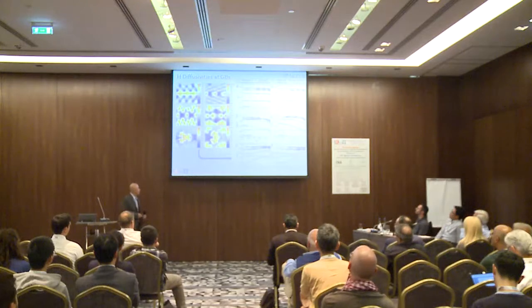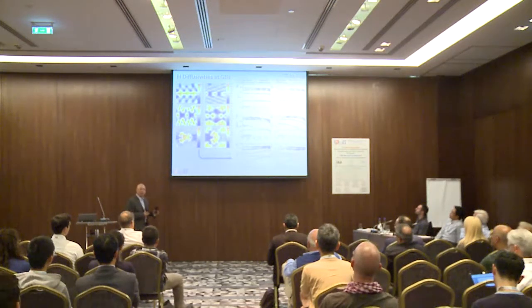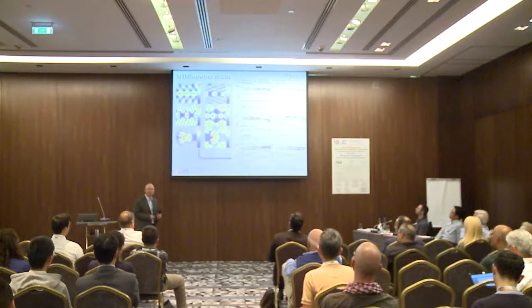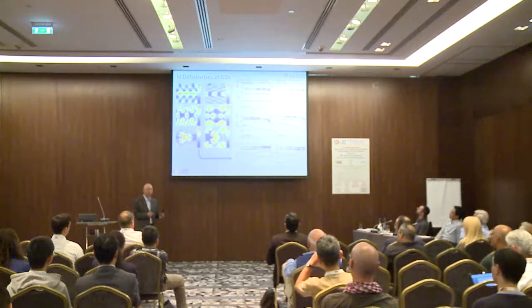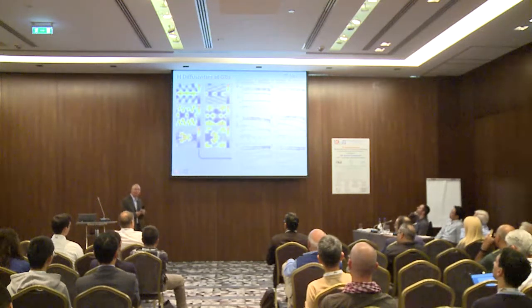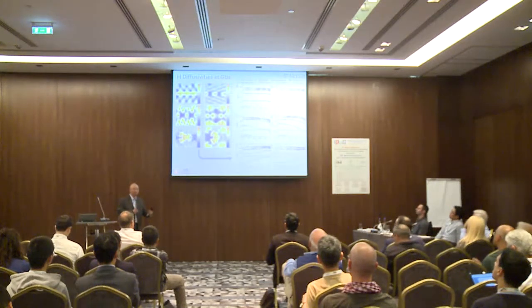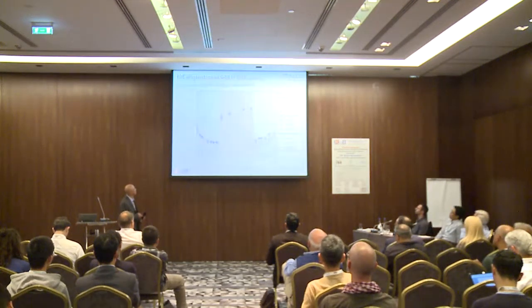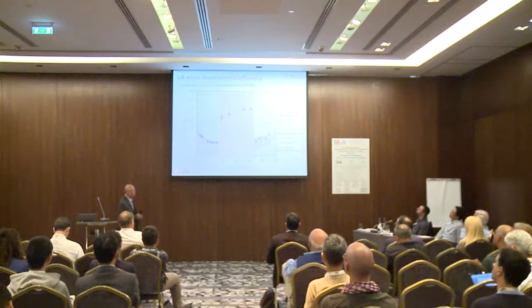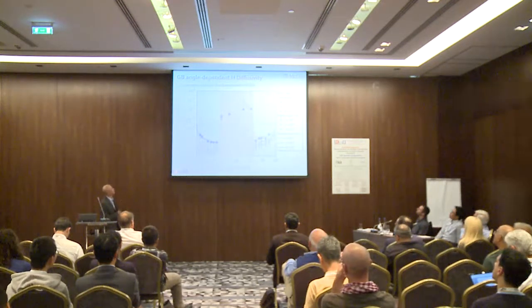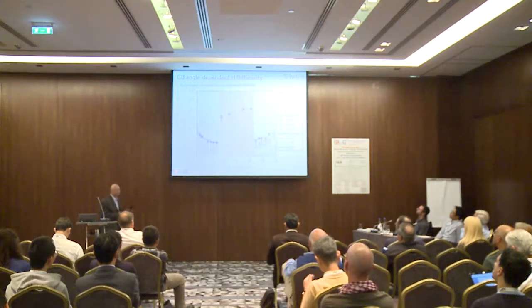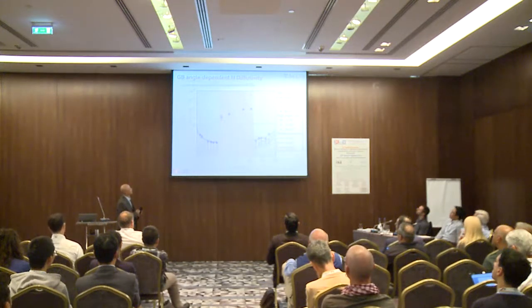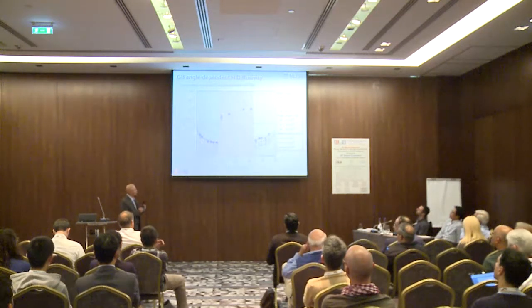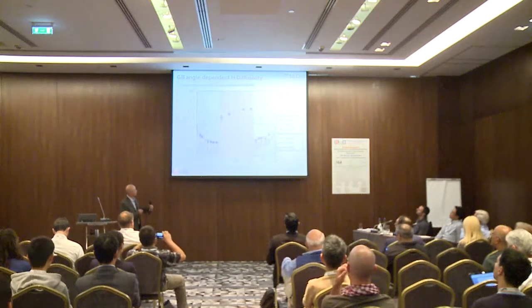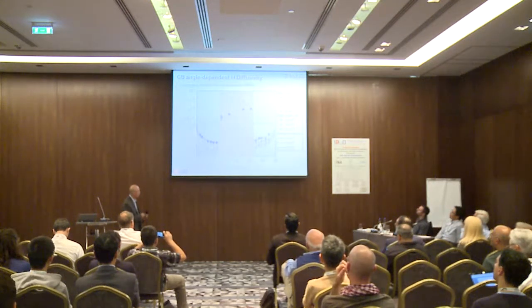Okay? So now we know that for different grain boundaries, you do have different diffusivity, but apparently that depends on the grain boundary characteristic. So how do we actually try to have a structure-property relationship? Okay, so for that, we choose a particular representative of grain boundaries, and we choose [100] symmetric tilt grain boundaries. Because this grain boundary is relatively regular, you can actually do good analysis of the grain boundary structure as you vary the tilt angle.